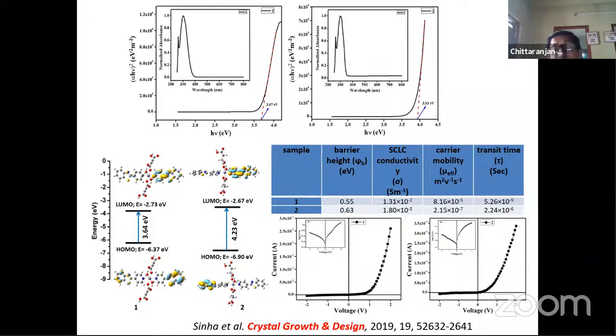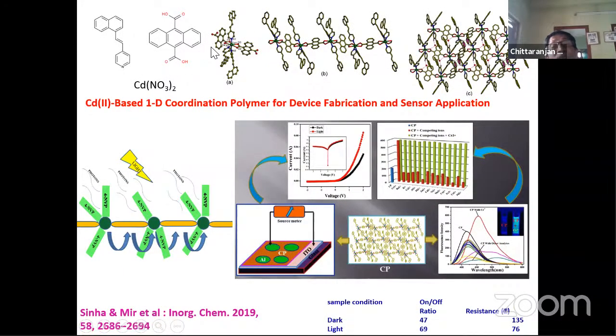Okay, not going into the detail, the only thing is that upon light radiation, the band gap is decreased, and that enhances the improvement in the conductivity. Herein we use another series of molecules, to increase the number of conjugated electrons in the bridging group, anthracene dicarboxylate. Anthracene dicarboxylate also initiates this charge transportation, and it shows a very interesting behavior because of this pyridine.